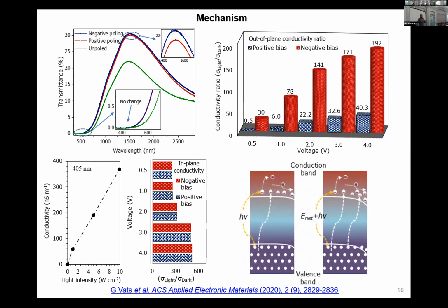So here is an exaggerated schematic of what is possibly happening in the sample. When you shine light, the charge carriers go from valence band to the conduction band. There could be an intra-band transition because the sample shows the bulk photovoltaic effect. As it is a non-centrosymmetric sample, there is a variation in the distribution of the charge carriers. And with applied field, we have more flow, which is leakage from here and here, and that's why we see all this.